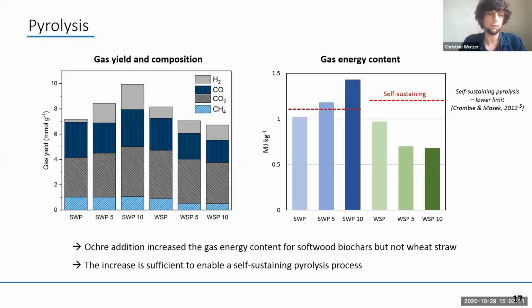SWP is softwood and WSP is wheat straw, and the number indicates the amount of ochre added. And here you can see that with the ochre addition, the total gas yield increases quite a lot, which was assumed from the influence of iron. And while CH4, CO2 and CO all are relatively stable, the hydrogen is increased almost 10 times the amount.